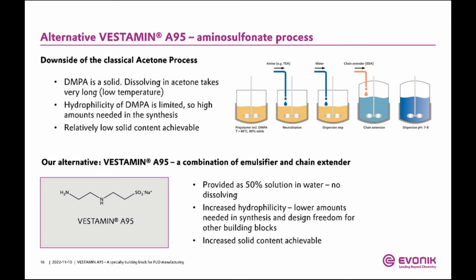In the examples I showed, we always went for a very high amount of A95. That means we aimed for the highest solid content, right? So we took the highest hydrophilicity possible to really optimize for high solid contents. If you don't do that, and you exchange part of your A95 and you're fine with the solid content of your existing system, and you just use it for the reasons of a simple process and more design freedom with other building blocks, and you exchange part of this with classical amines to do the chain extension, then you also get way better and comparable water resistance than with the DMPA system.